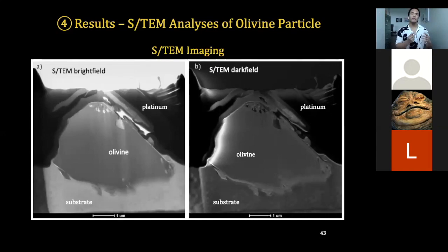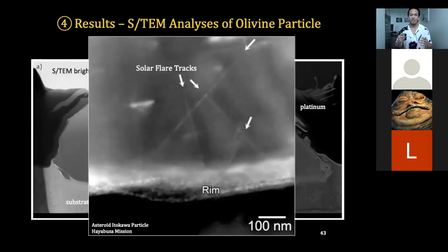The reason for getting both the bright field and the dark field imagery is because some features visible in the bright field are not visible in the dark field and vice versa. Getting both of these images and comparing them side by side allows you to not miss any potential features. As far as features that we were looking for, solar flare tracks. An example of that is this particle from the Hayabusa mission. This particle is an asteroid particle, and you can see that it has spent a significant time in space, indicated by the solar flare tracks that look like straight white lines going in different directions. So it doesn't have a normal pattern.